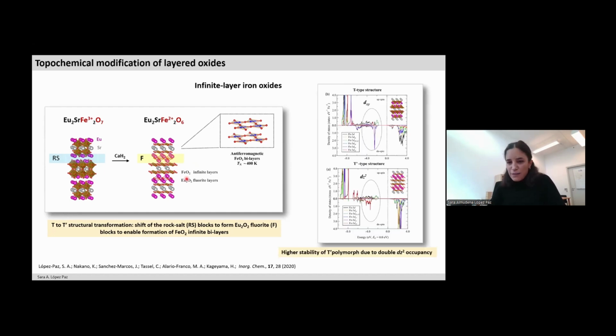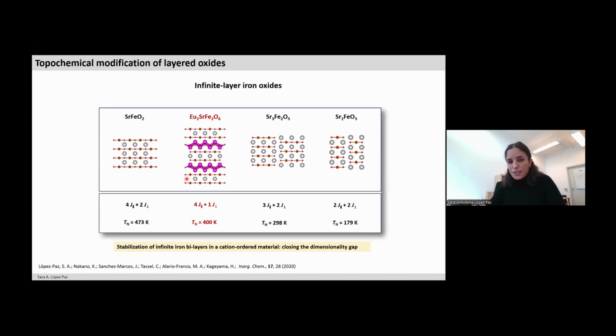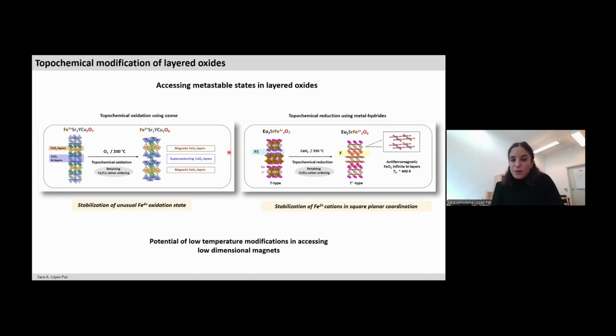So we also studied the effect on the electronic properties of this structural reconstruction, but to me the most interesting point is that in this way we show how combining this low temperature approach with cation order, we could extend this family of compounds and actually close the gap in the dimensionality. So I think these two examples show that this low temperature approach for the synthesis of low dimensional magnets is actually very promising, and made me want to explore a bit more how to access low dimensional materials.